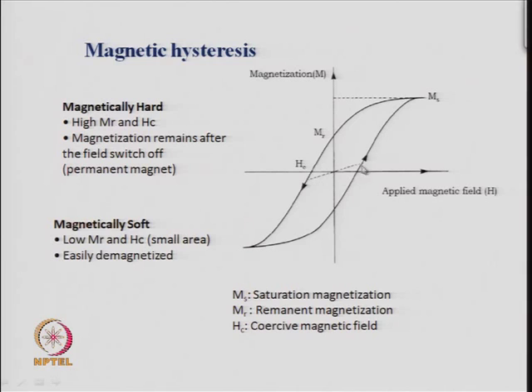So, what we learn from this hysteresis loop typical for ferromagnetic materials is that you will get a saturation magnetization, you will get a remanent magnetization when the field goes to 0, when you are doing this cyclic loop, and when you take the field further in the other direction, you will get a net magnetization equal to 0 only at a field which is Hc and is opposite in direction to the original field applied. And then you further increase the field in the negative direction, and the magnetization changes sign.